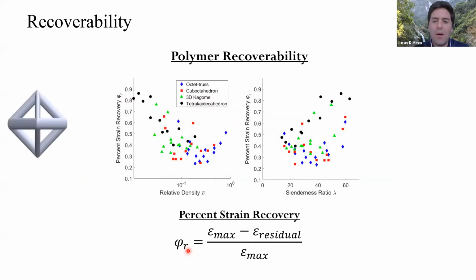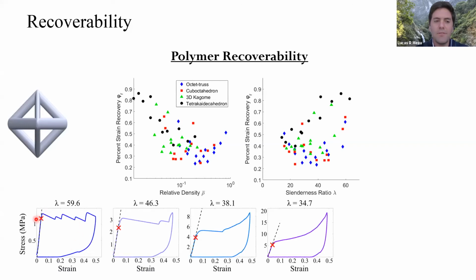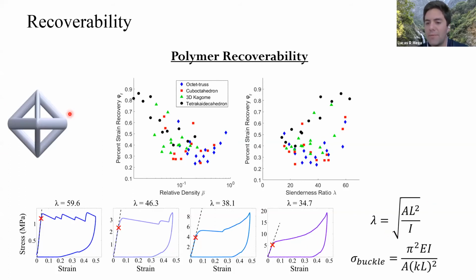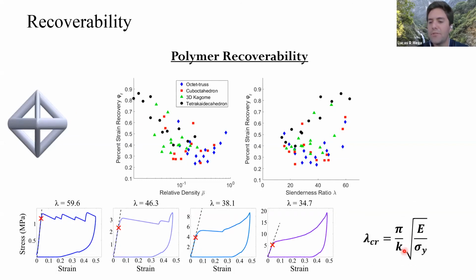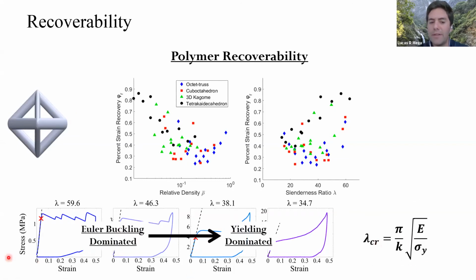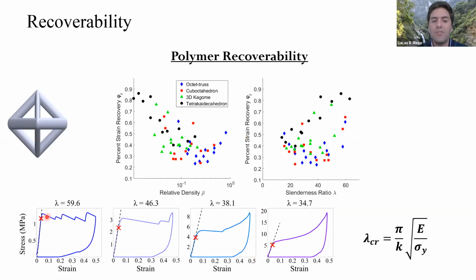So we looked at polymer structures. For polymer structures, you can define a figure of merit lambda for the slenderness of a beam. You can relate that to the buckling limit of the beam, and find a critical transition where you go from Euler buckling dominated to yielding dominated behavior. You can see qualitative changes in behavior, the sort of bursting event - these are Euler buckling events, and this is densification and plastic yielding.